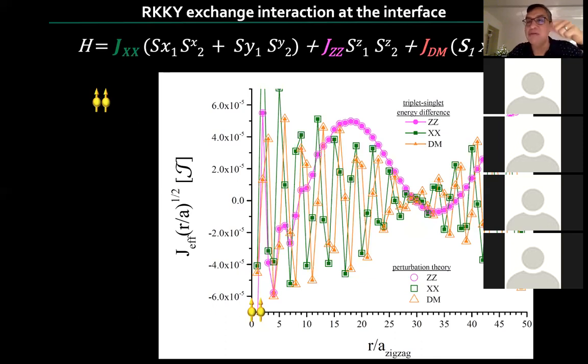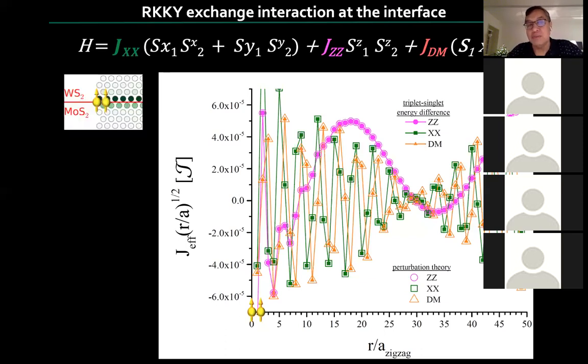This is very peculiar because even in metals, in heavy metals like platinum or whatever, the Dzyaloshinskii-Moriya is typically much weaker than the direct Heisenberg interaction. Well, here we see they're comparable. And that is this peculiarity of this system. So it's very unique in that respect. Again, the electrons that mediate this interaction will sit on both sides, straddling the interface. And so they bring all that information to the scattering. Oscar made this animation where you can see, depending on where the impurity is, the equilibrium configuration changes from being ferro to anti-ferro.